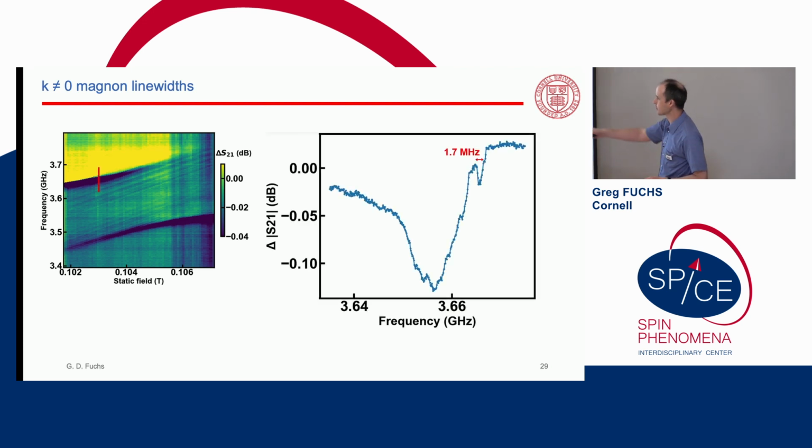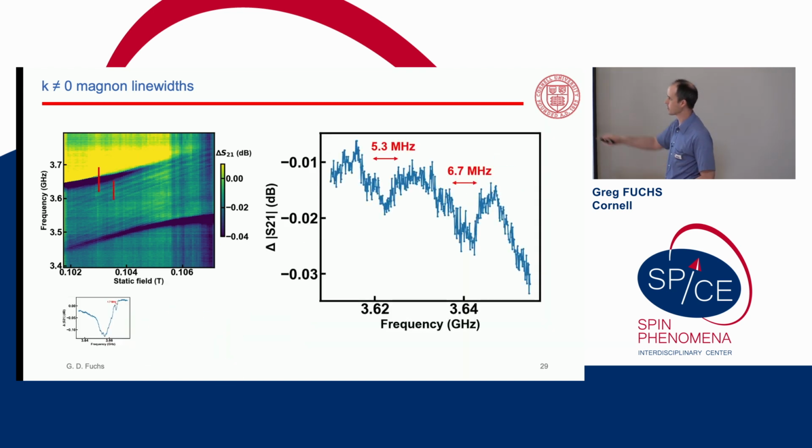Well, if we actually look at the fine details of this plot where these higher order modes are dispersing, you can see that they actually do have a narrow line width in the line cuts. So there's, for instance, n equals 8. Here's some of the lower modes from these line cuts. This is getting now to the signal to noise of around 2, so it's not the best data that you've seen, but they very clearly only have a few megahertz line width.